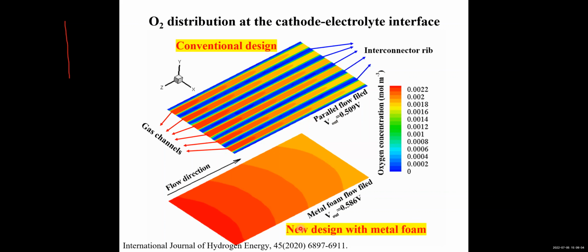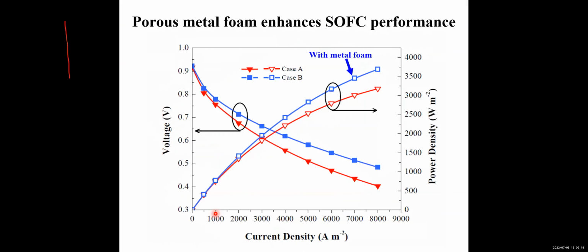However, when we use metal foam to replace the rib of the interconnector, we can provide more uniform oxygen distribution over the entire cathode, which improves the cell performance. Based on the calculation, using metal foam to replace the rib, we can successfully improve the power density of the large scale cell. So this is very successful.